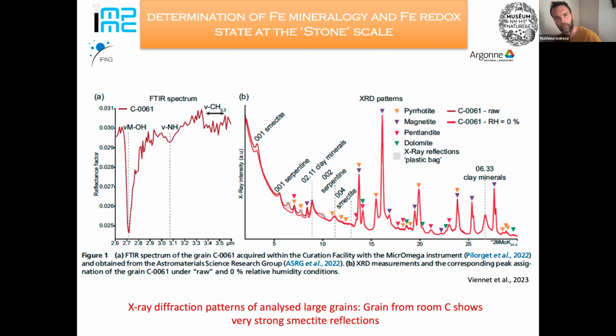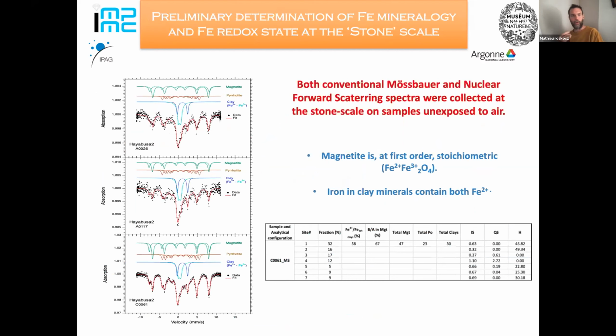But we did not pay much attention to this dolomite for the NFS. The first thing that we did, because we were lucky to have one large grain, about 400 microns in diameter, was to collect a conventional Mossbauer spectrum. This is the C0061 spectrum at the bottom. And after a couple of weeks, we were able to have a pretty good MS spectrum.